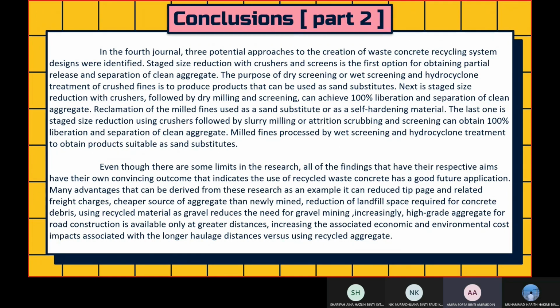The last one is staged reduction using crushers followed by slurry milling or attrition scrubbing and screening, which can obtain 100% liberation and separation of clean aggregate. Milled fines are processed by wet screening and hydrocyclone treatment to obtain products suitable as sand substitutes. Even though there are some limits in the research, all of the findings, with their respective aims, have their own convincing outcome that indicates the use of recycled waste concrete has a good future application.